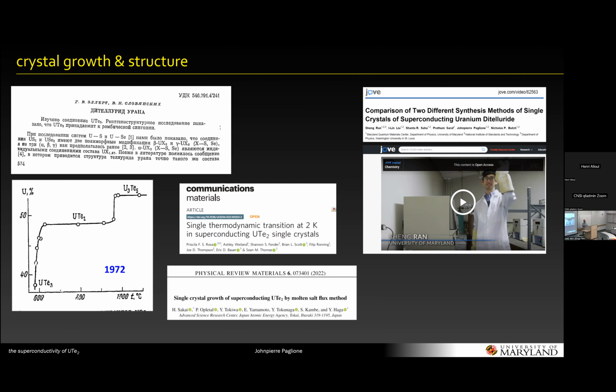My point is, how can you be sure now that when you compare different samples processed in different laboratories that they are identical? You were telling us that it's very reproducible. It doesn't seem to me that it is the case. For instance, if I grow crystals in a vapor transport growth and change the temperature from 950 C to 850 C, I can increase TC from 1.6 to 2 Kelvin and get various physical properties that we measure that are nearly identical to what's done in Los Alamos or in Japan, using the same kind of parameters. Different furnaces, different materials, everything different, but roughly speaking, very similar properties. That's the reproducibility I'm talking about. There's reproducibility, but not control.